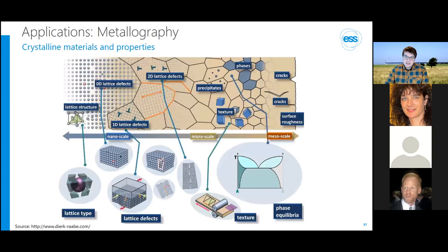So if we stick with metallic materials, or generally speaking, crystalline structures for another moment, the previous example has shown that we can see the rather large cracks of the metallic sample that you can see here. But if you now want to study smaller features like these precipitates, for example, or derive information about the crystalline phase or texture, then the normal attenuation imaging that I've just shown you won't be able to resolve this. These properties range from atomic or angstrom scale up to the macro scale, which means up to millimeters. Neutron methods, as you have seen on the previous slides, can, however, access all of these length scales.